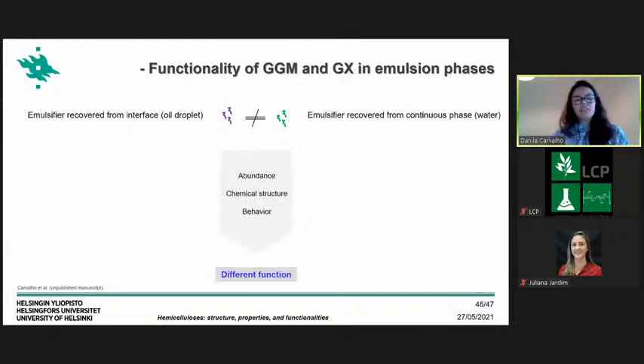And by collecting these different fractions of GGM and GX, what we could see was that they differed in terms of abundance, which means that the amount of GGM and GX in the oil droplet differed from the continuous phase. Also, the chemical structure was different and the behavior was different. And this suggests to us that the function of the emulsifiers at the droplet interface is also different from the function that they perform in the continuous phase.